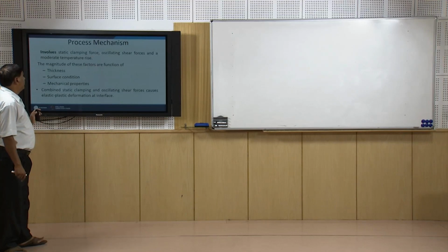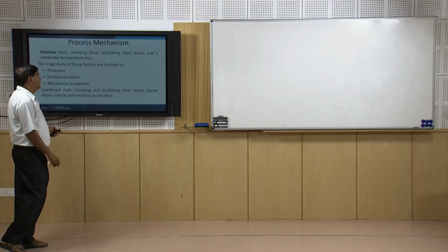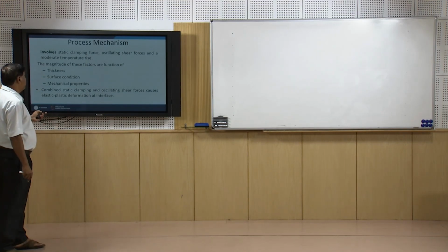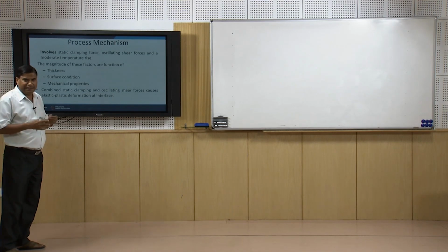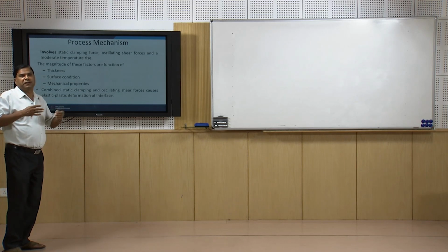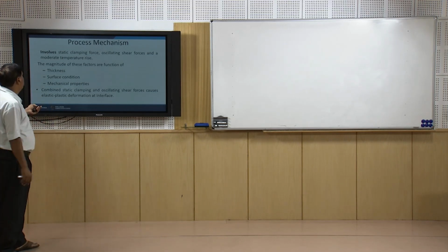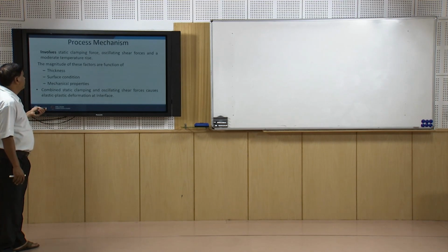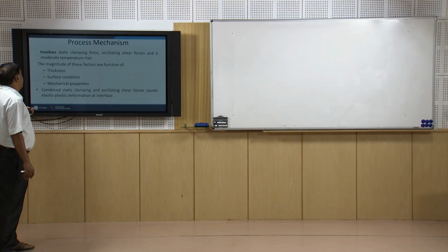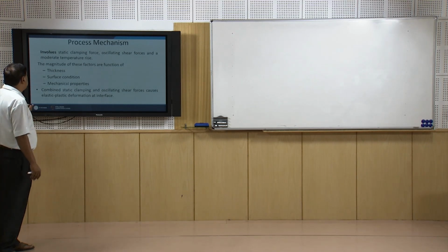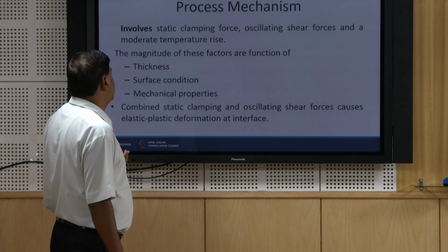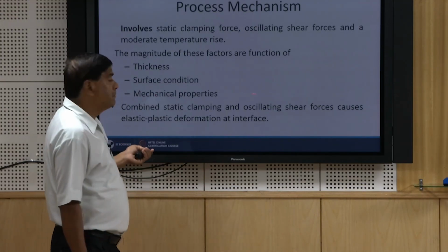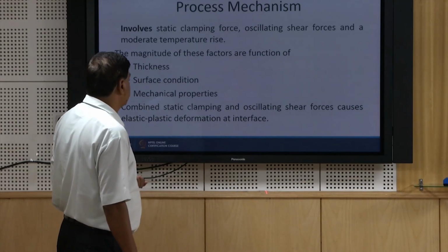The different variables that affect the success of the process: one is clamping force and oscillating shear force, and under the process conditions, due to the friction and deformation, heat is generated. So, the heat generation is moderate, and these factors, the clamping force and oscillating force magnitude, their selection depends on the thickness of the sheet to be welded, hardness of the material and yield strength, and the surface conditions, of course.